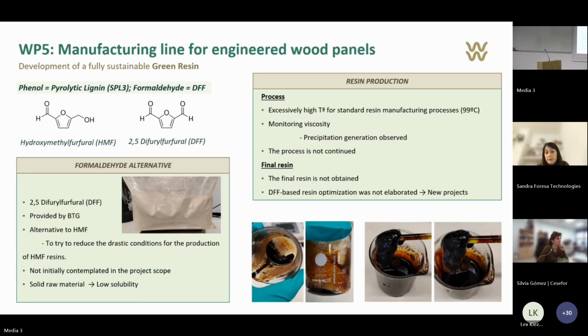In view of the harsh conditions required to elaborate a 100% bioresin, the use of DFF has been proposed as an alternative to HMF, although, as I said before, it was not initially contemplated in the project scope. Trials with DFF reveal significant technical issues. The solid nature of DFF requires a temperature near 99 degrees for dissolution, which is industrially impractical. Moreover, during the polymerization process, precipitation was observed and could not be removed, as you can see in the pictures. Therefore, the elaboration of this resin could not be continued, and it was not possible to obtain it.